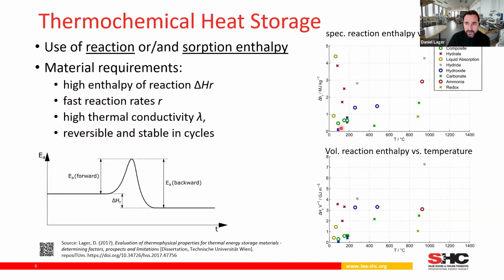Here on the right side, you see some of the known materials which are also in the literature. For example, when you look at physisorption, which can be a zeolite material, you're in that range of the reaction enthalpy at lower temperatures. But in comparison, for example, to an oxidation reaction, you have higher temperatures and also higher reaction enthalpies. So this is just some introduction into the different materials and the quantities you need to know to identify if your material is good for the application you plan or not.